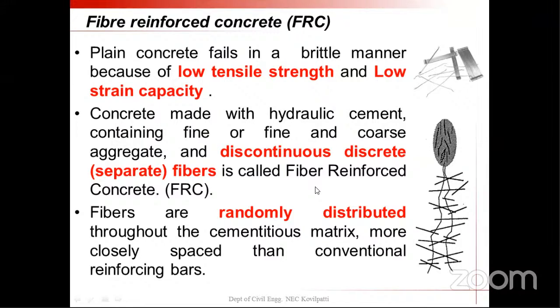So one special thing about fiber reinforced concrete is that the fiber is distributed throughout the entire composite. Suppose we want to improve the tensile strength by means of conventional reinforcement bars, these bars will be located only at the specified locations. So it will improve the tensile strength only up to the peak tensile strength. Whereas in fiber reinforced concrete, the fibers are distributed throughout the cement matrix, and the fiber spacing is also very close. So it will improve the overall behavior of the cement composites.